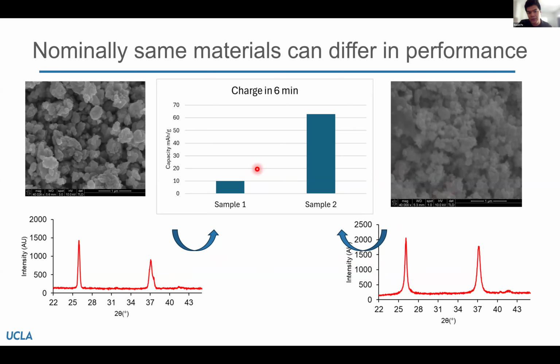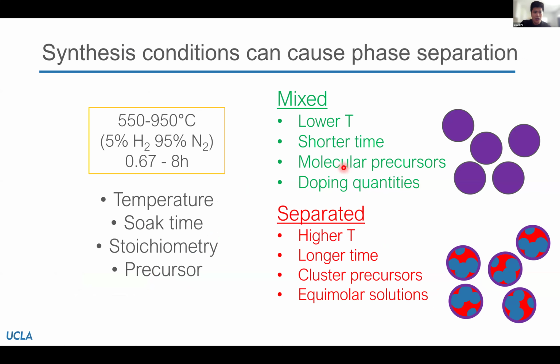speed. If we look at a metric like how much charge you can get in 6 minutes, so a very fast charging speed, we can see that two samples that are nominally identical can get upwards of 6 times the capacity in samples that should be, at least from bulk analysis, very similar. And so the reason for this, we've discovered, is that even though you're able to index a certain material to a certain phase, at a nanoscale, there might be a level of separation.